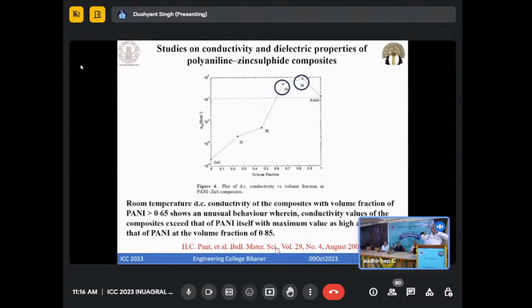Now we know that when you make a mixture of the two, what will happen? When you take zinc sulfide, low conductivity. When you take polyaniline, high conductivity. And as you change the ratio, conductivity will move from lower to higher side. But closely observe these two circles, wherein you are seeing that these two composites have electrical conductivity higher than that of polyaniline. How can it be? A composite is made, how can the conductivity be higher than the highest?